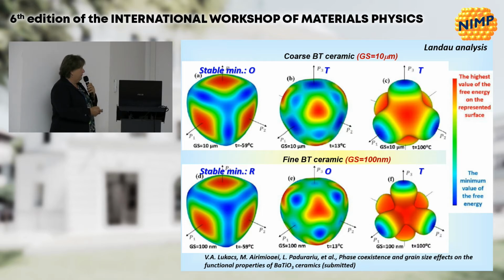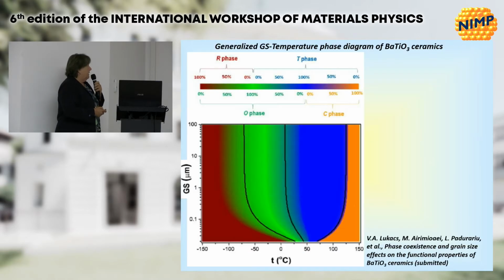But here, before that, I wanted to show that for the same temperature, a coarse ceramic can be orthorhombic and a fine one can be rhombohedral, or at 13 degrees C, for example, the coarse one can be tetragonal and the fine one can be orthorhombic, or above 100 degrees C both can be tetragonal, and in the paraelectric case they can be cubic, of course.